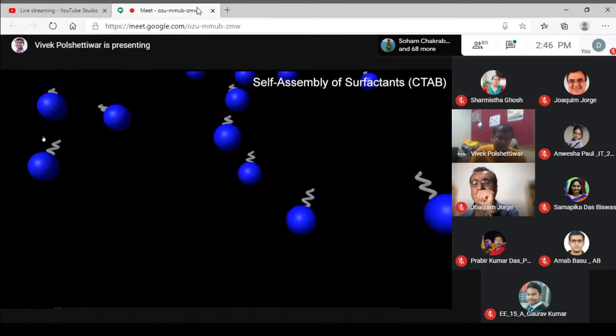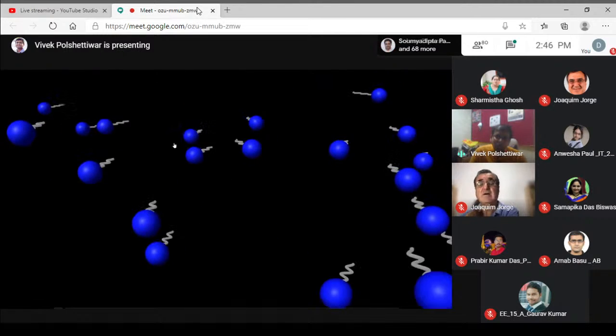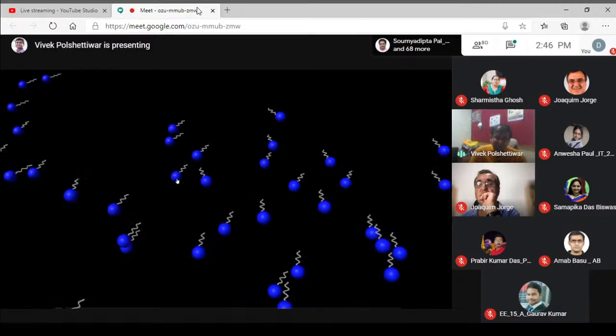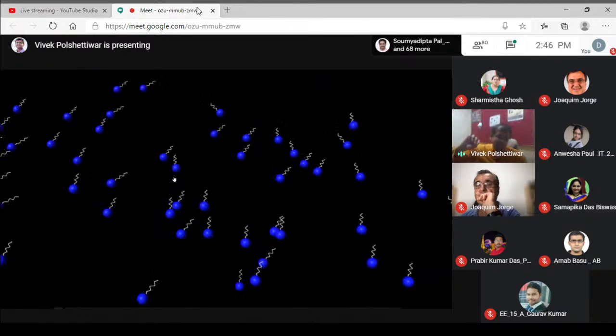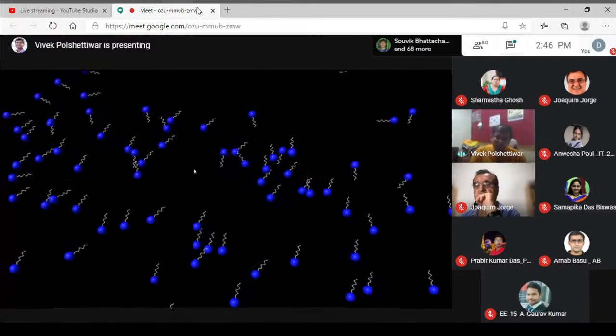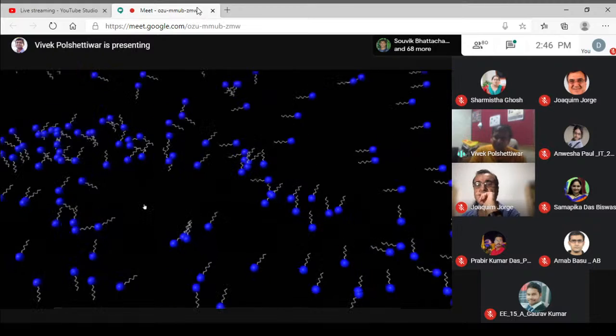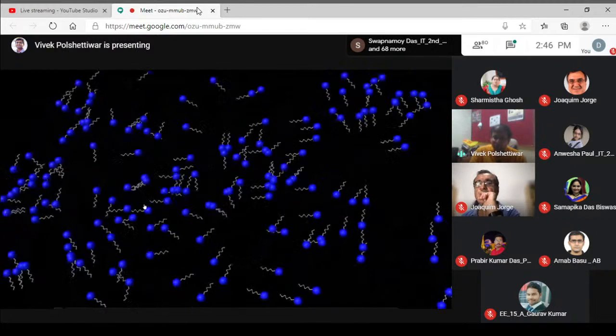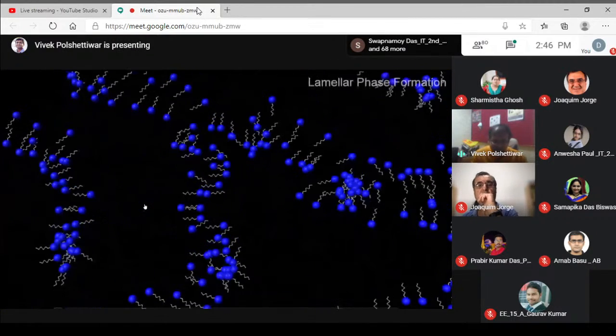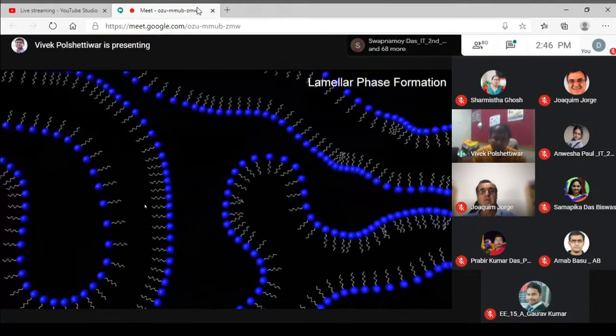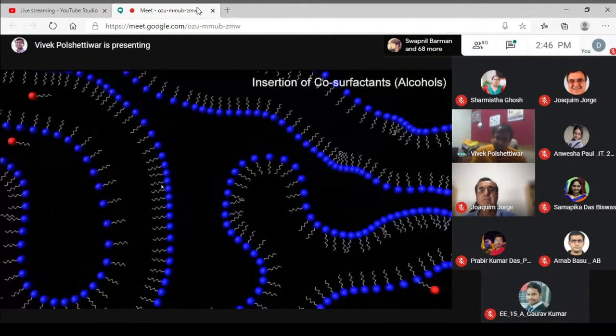So these are the template molecules. The blue ball is quaternary nitrogen, and that zigzag line is a C16, a non-polar tail. So what happens whenever you add these surfactant molecules into the solvent? Here we're using water and xylene. They try to minimize the total energy of the system by self-assembling and forming these lamellar phases.